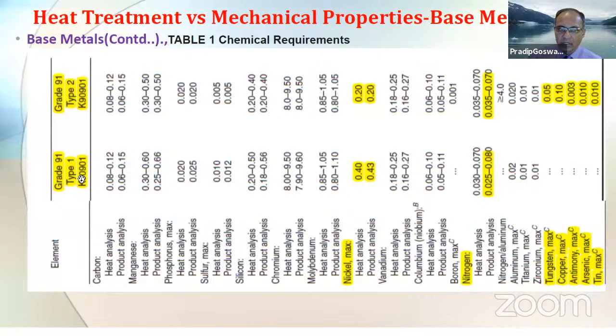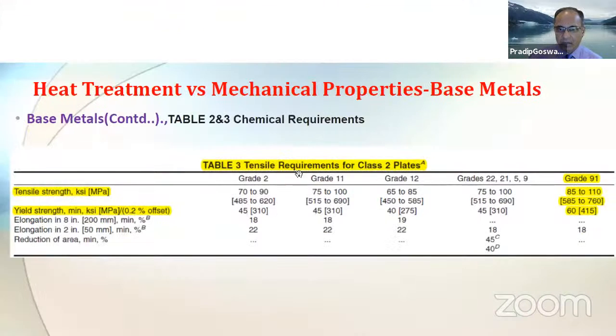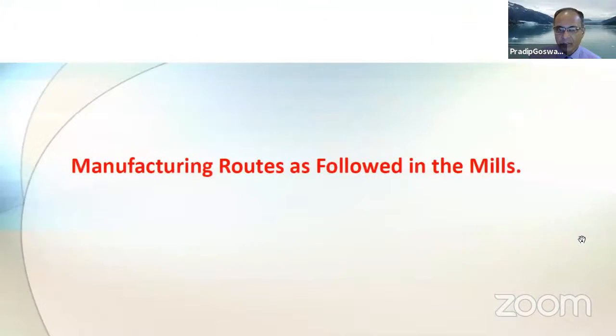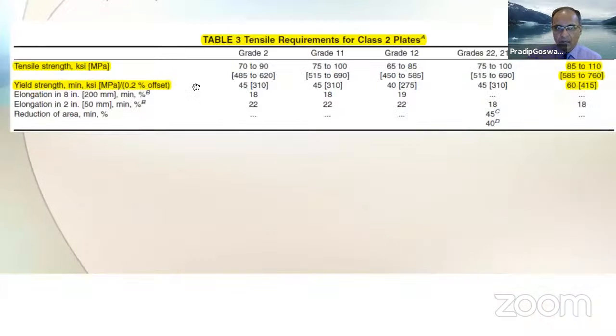So here it tells about typically the composition for plates for grade 91, type 1 and type 2 steel under the specification A387. And this table talks about the tensile requirements for the class 2 plates, and you see here grade 91. These are the typical recommended mechanical properties as per the code. So up till now, these few slides give the typical mechanical conditions, conditions of delivery, as well as the heat treatment which the steel would require before it is delivered to a fabricator's shop.